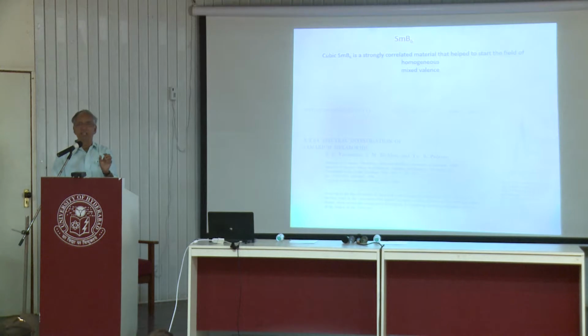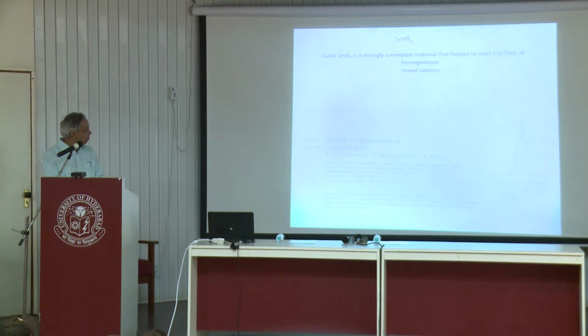What was known is that people tried different materials and concluded there is a difference of something like 6 or 7 electron volt if the 4f orbital electron count differs by 1. In other words, if you take the samarium 2+ state and do X-ray absorption, you will get one peak. If you take 3+, you will get one peak, but the position will be shifted by typically 7 electron volt.